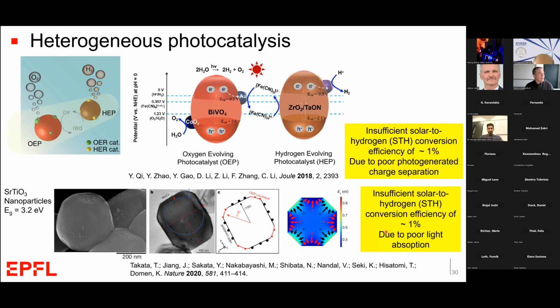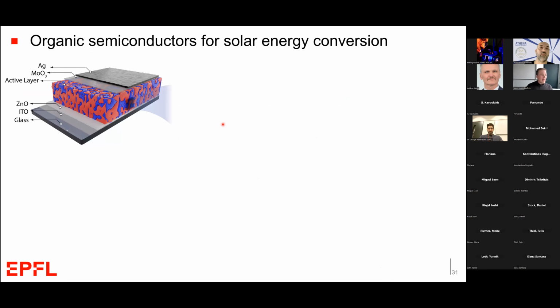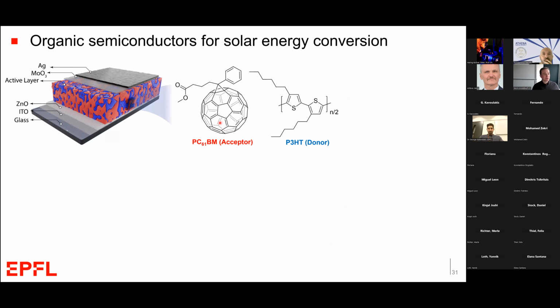So one challenge in the field of heterogeneous particle-based photocatalysts is to develop systems which can separate effectively the electron and hole after they're photogenerated, but also have materials that absorb a lot of light. There's one system that caught our attention as being capable to separate photogenerated charge carriers on this sort of nanometer scale, and that's the organic bulk heterojunction type systems. So you may be familiar with the organic photovoltaics that typically use a blend of a donor and acceptor material like this, and that blend is made on a sort of a nanometer length scale or a bulk heterojunction in the active layer of a device like this.